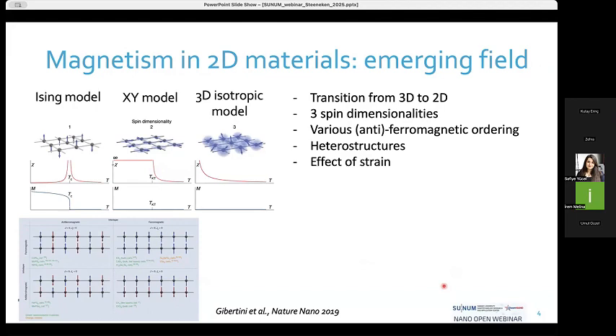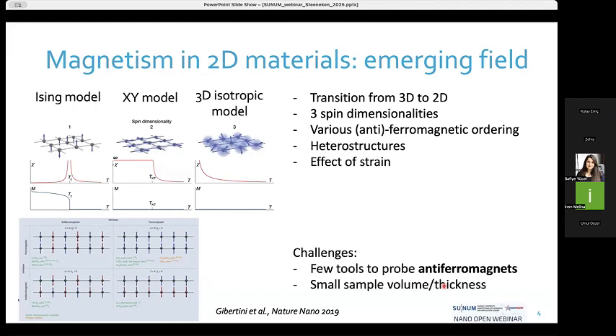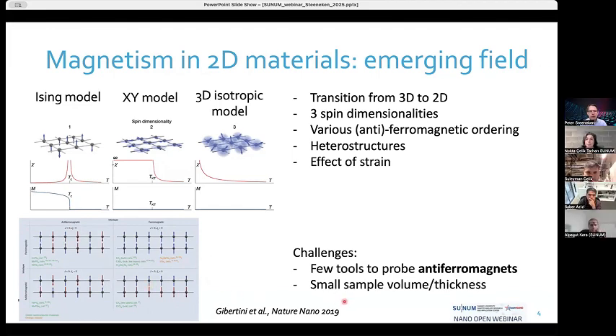We would like to investigate this, but this is not easy because there are very few probes to actually detect spins in such a thin layer. Especially when the material becomes antiferromagnetic, the magnetic fields of these spins are canceling each other, and it's very hard to detect. And of course, the volumes of these samples are very small because they are only 1 atom or a few atoms thick. So we set out to see if we could use nanomechanical resonance as a tool to probe these new phases of magnetism.